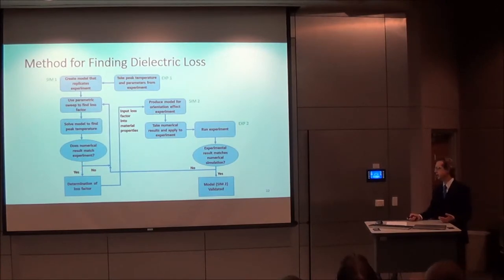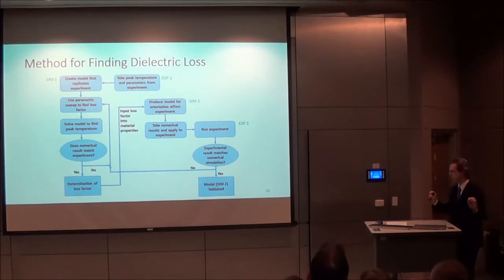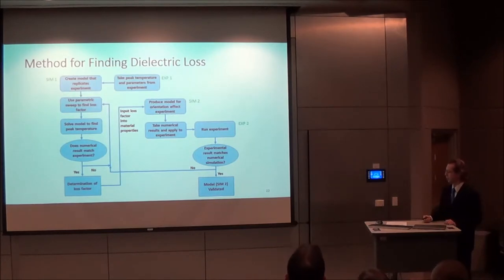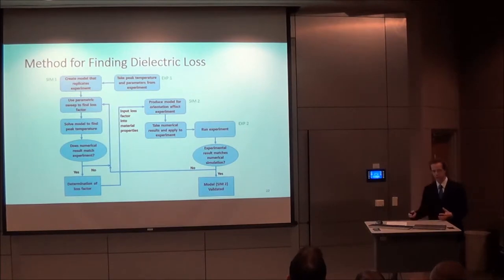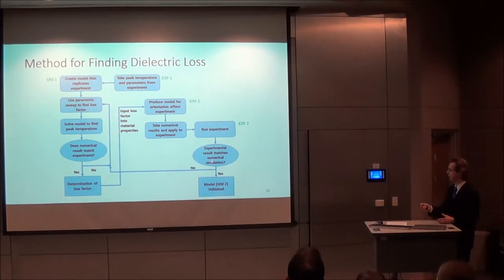If it doesn't, this is repeated. If it does, then we know that this is the loss factor that is present in the material. And this is used in a new model, so this loss factor is used to calibrate a new model that will be used to study the orientation effect in this particular example. And the results of that model are taken and compared to an experiment. The experiment uses the same geometry of the chamber, et cetera, and the experimental result is compared to the numerical results. If they don't match, then go back and try to find a new loss factor.